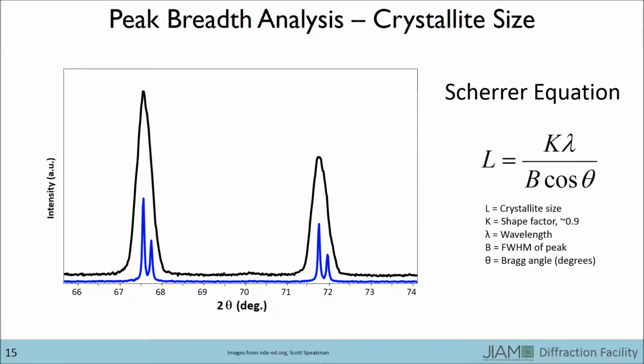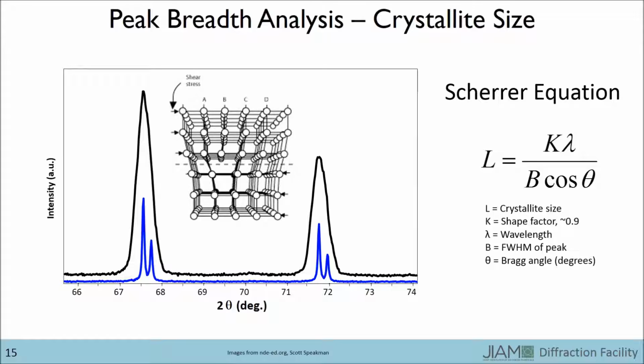Another issue is that in addition to instrumental broadening and broadening due to crystallite size, microstrain also affects the breadth of your peaks. For instance, imagine that you have a crystal lattice with an extra half plane of atoms. The d-spacings for the atomic planes around this extra half plane of atoms now vary instead of being the same. If we were to take these d-spacings and apply them to the diffraction pattern, we can see why microstrain broadens the peak. Recall that every d-spacing corresponds to a particular value of 2 theta that brings about a peak. If the d-spacing of a particular plane now has a variety of values larger and smaller than the average, this means that the angles larger and smaller than the Bragg angle will also bring about some sort of intensity, thereby broadening the peak.